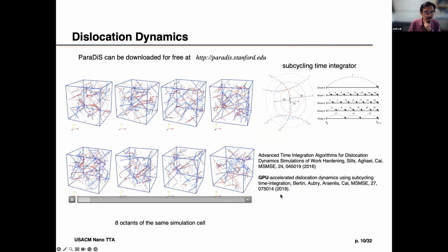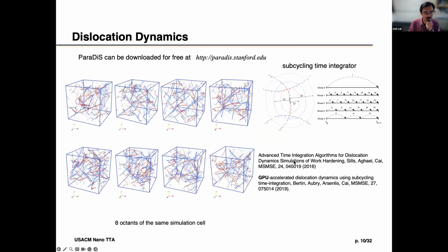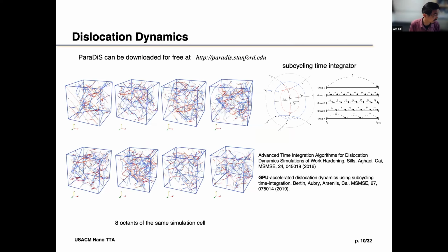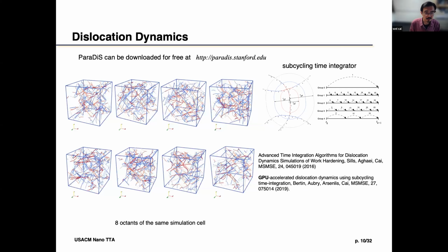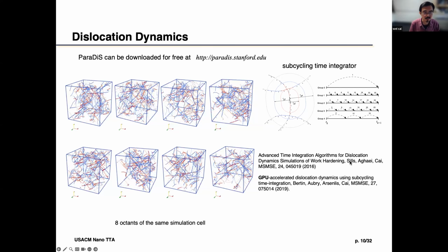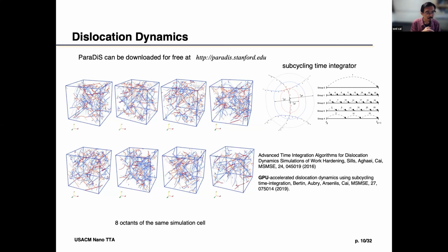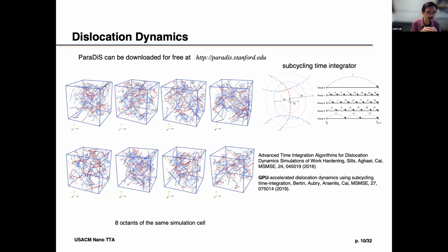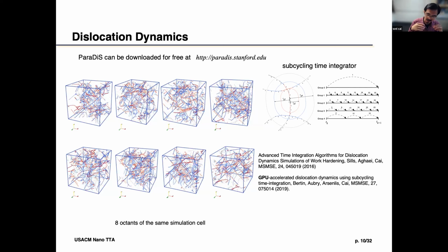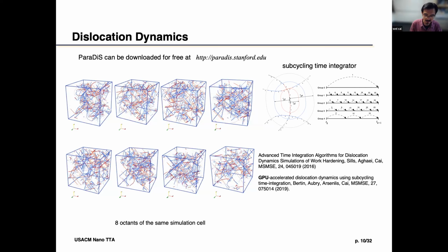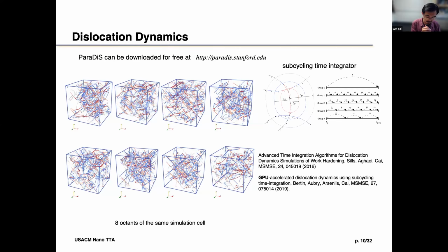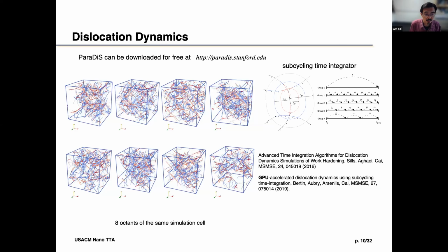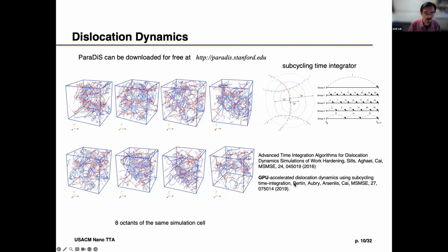Now, before about 10 years ago, we had always been suffering from the high computational cost of discrete dislocation dynamics simulations. So about 10 years ago, my former student, Ryan Sills, looked into that and developed a better time integration algorithm, where you separate out the different contributions to the dislocation velocity and handle different ones using different time steps. It's a subcycling algorithm, and that really made things much faster. And then later on, Nicolas Bertin, who's now at Lawrence Livermore, ported that algorithm to the GPU, and that really made it much, much faster.